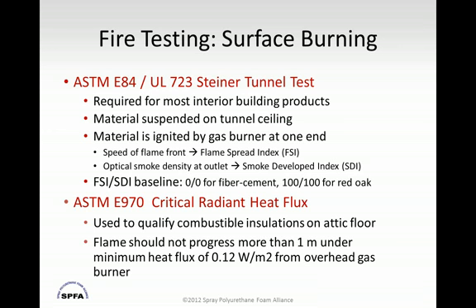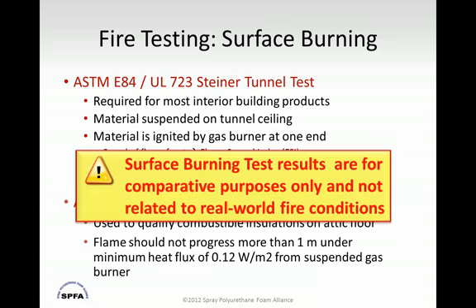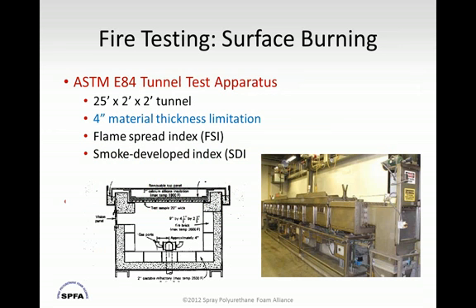In addition to that, spray foam is also using ASTM E970, the critical radiant heat flux test, used to qualify combustible insulations in the attic, including cellulose. And what this small test says is that the flame should not progress more than 1 meter under a heat flux above the floor of 0.12 watts per square meter from an overhead gas burner. Again, these surface burning tests are used for comparative purposes only and not suitable for relating to real-world fire conditions.